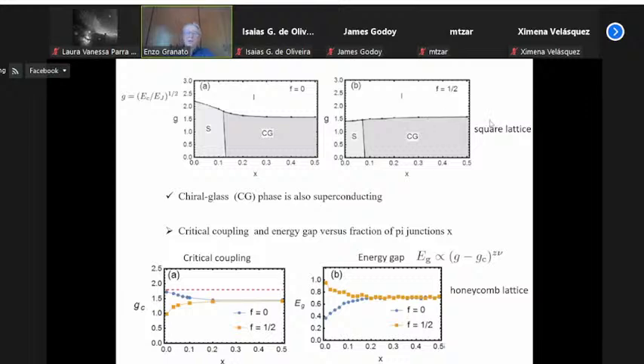And this is for the square lattice, but for the honeycomb array, this is more clear. So here I plotted the critical coupling for zero field and for 1/2 as a function of disorder, and you see the critical coupling decreases for zero field, increases for 1/2, with an inversion at a particular point. And this particular point in which the inversion happens is the entrance into the Chiral glass phase. So the Bose glass phase is a superconductor. That's the critical point of the result of this calculation.